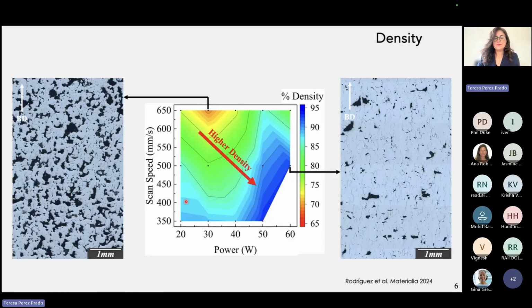Let's start with the density. So here we have a color map showing the density with respect to the scan speed here and the laser power, all within this low power region that I mentioned, the region where we are at least able to print the shape that we want. And we have here two bad news. The first bad news is that, well, no, not yet. Sorry, not yet. The bad news comes later. But what the news, of course, is that we are not printing a fully dense material. The maximum density here is close to 95%. It's about 93.7 or so. The lowest density here is more close in the 60s.